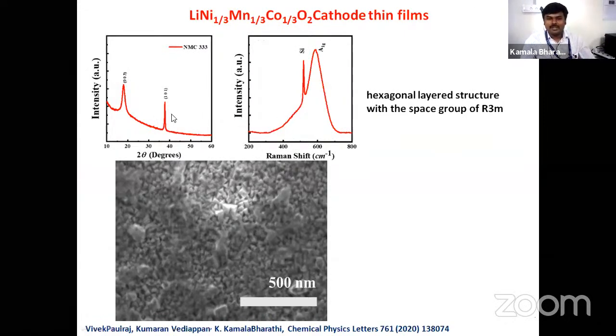These two data confirm the formation of this film in a hexagonal layered structure with the space group of R3M. And SEM morphology tells the triangular morphology of these films, and lithium can diffuse through these gaps between these triangles when we do the electrochemical test.